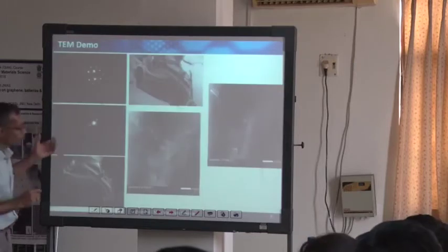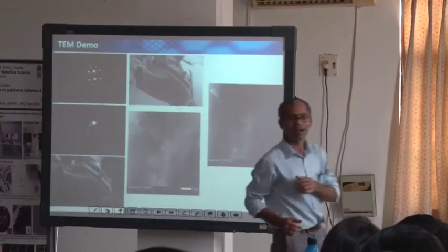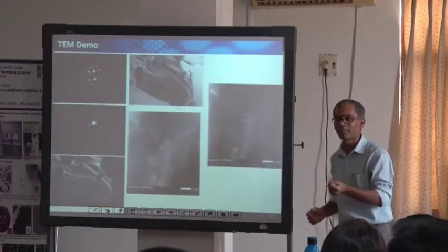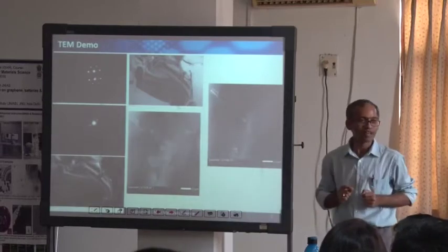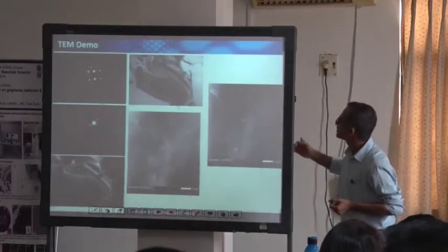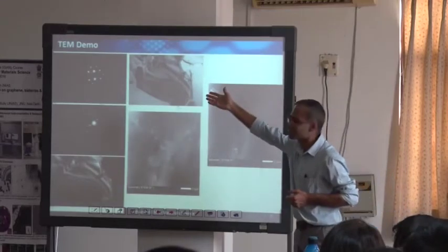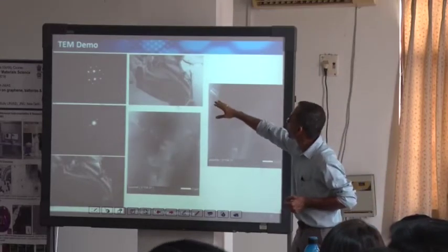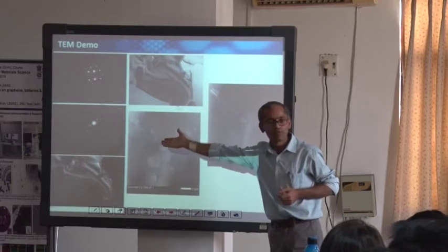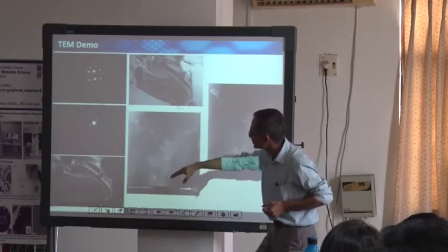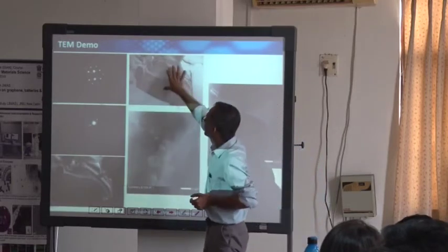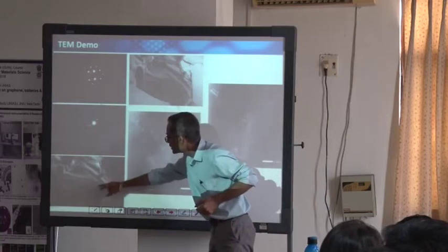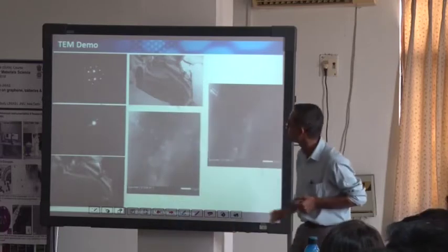Okay. So we had chosen an aluminum sample, our common packaging foil, and we studied its microstructure. You have the zone axis diffraction pattern and the bright field image. We tilt it into two-beam conditions, and then we get this dark field image. So we find out the grain size, and we can see some precipitates, grain boundaries, dislocations, etc.